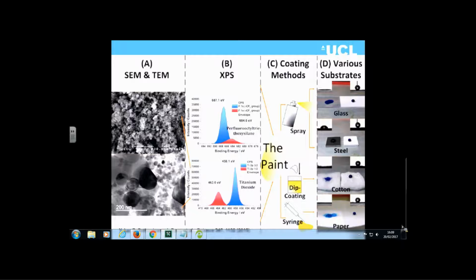What we do is reduce the amount of abrasion that happens when you rub the surface. Instead of rubbing off the surface features, you push the surface roughness into the elastic or polymer layer, and as soon as you take the shear force off, it pops back out. So instead of rubbing off the surface, you push it into the elastic layer, giving rise to a high degree of stability.